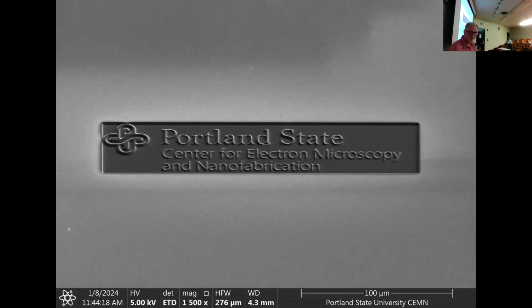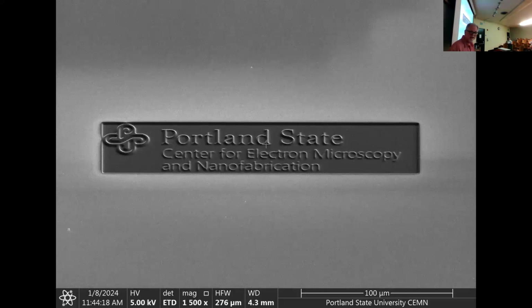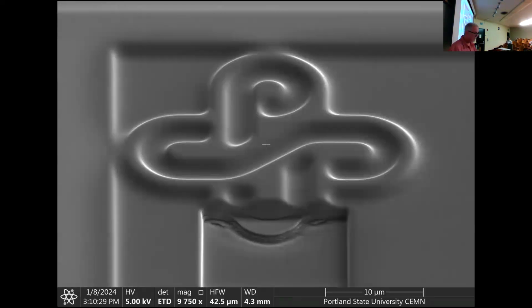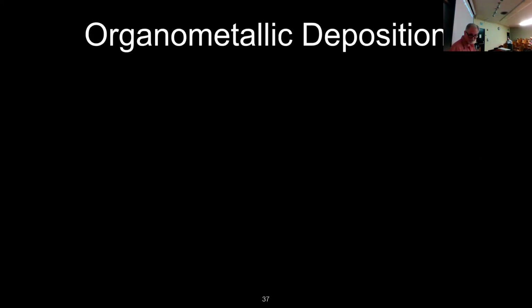But I was pretty happy with it. I liked it. I knew that there was going to be some defects. We can see on the left of the S how that's not fully developed, and at the top of the P that's not fully developed. That's because it's at the edge of the logo. I could fix that by modifying the logo, putting some white in. And I did a little cross section here so you could actually see the rounding. Poor PSU logo. The actual logo itself is about 30 microns in this view.